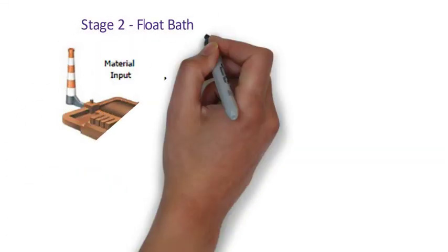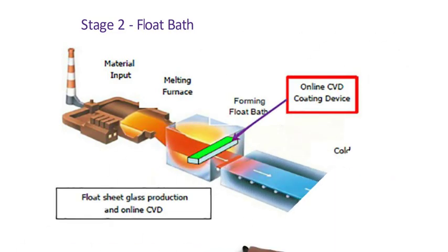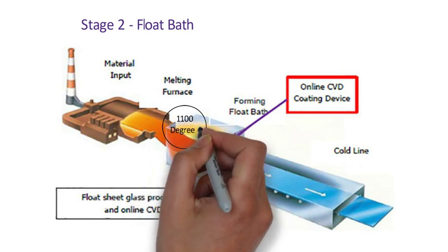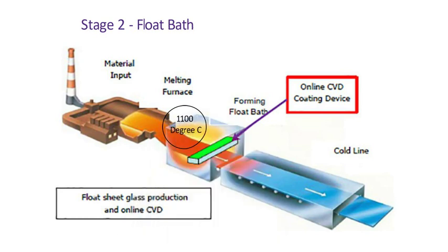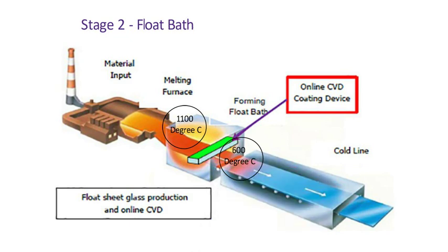Glass from the furnace gently flows over the refractory spout on the mirror-like surface of molten tin. Starting at 1100 degree Celsius and leaving the float bath as solid ribbon at 600 degree Celsius. In this process, a desired thickness of glass is achieved.